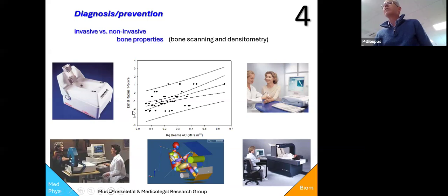So for instance, here we have the fracture toughness of beams of bone from, I think, about 36 individuals, and the T-score that came from ultrasound measurements of the wrists of these same people.